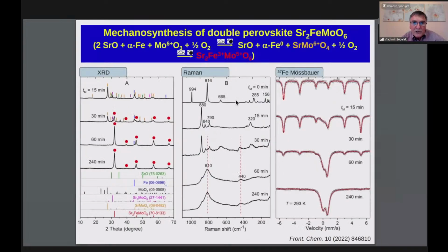In many cases, as I mentioned, mechanochemical synthesis of complex oxides goes through formation of intermediates, as demonstrated for the mechanochemical synthesis of double perovskite strontium iron molybdate. You see that we started now also from three reactants, but it is a heterogeneous reaction involving oxygen from the vial in the milling chamber. You see X-ray diffraction patterns, Raman spectra and Mössbauer spectra showing disappearance of the fingerprints of reactants and formation of the double perovskite after